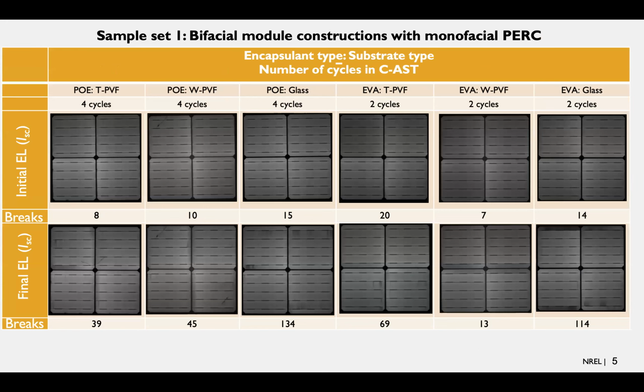So the interesting results here are in the electroluminescence, where we're looking at the initial electroluminescence and the final electroluminescence of all those samples. One of the things we notice is that the samples with the glass substrate, whether it be polyolefin or EVA, seem to show the most grid finger breaks when examined after the end of testing.